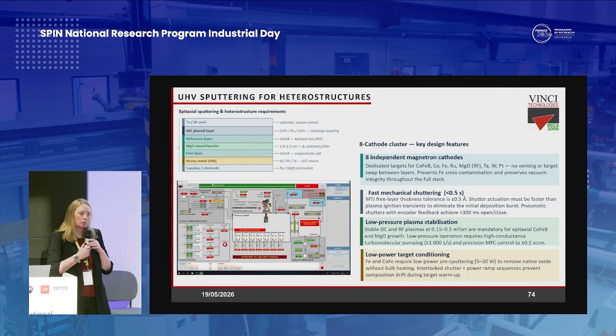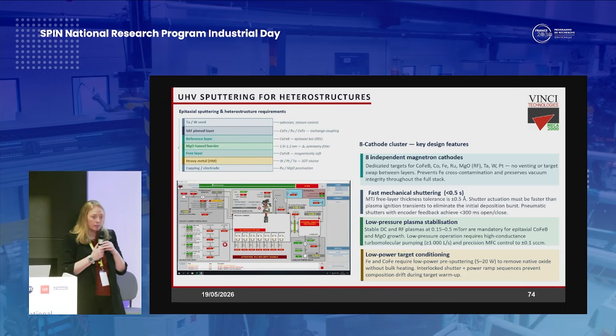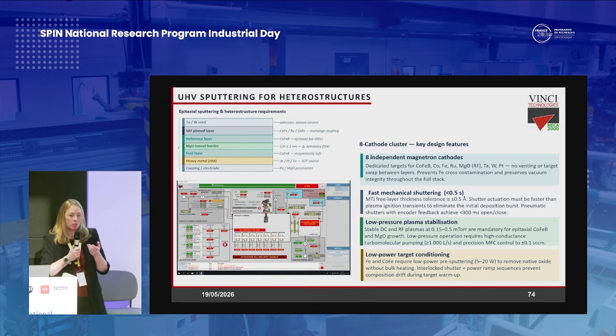So using different design features such as double-walled cooling, or limiting through shielding the variations on your pressure, such that you can ignite the plasma at around 30, 40, 50 watts and then reduce in terms of pressure and in terms of power in order to maintain the plasma for long periods of time is quite challenging. And the influences during the growth of different heating and parasitic plasma that can happen within the chamber requires a lot of interaction actually with our end users.